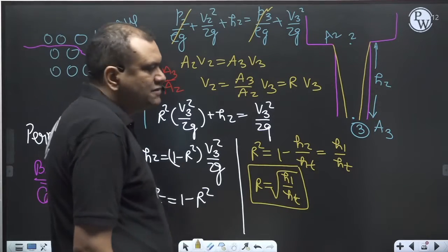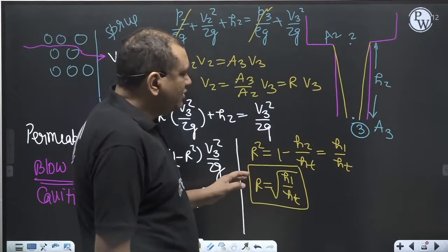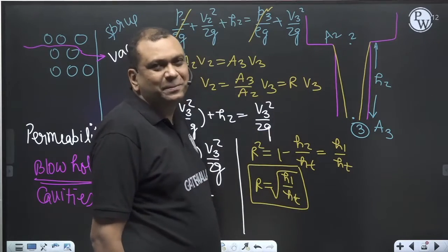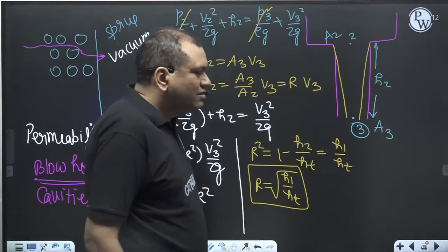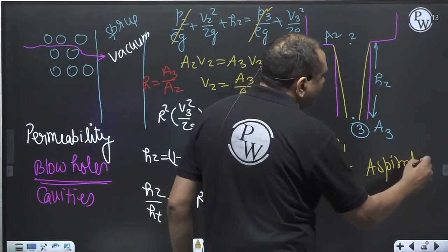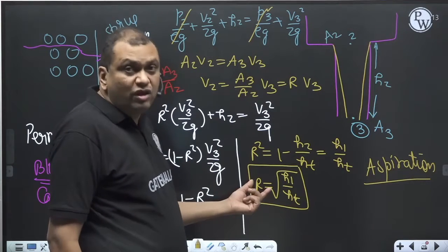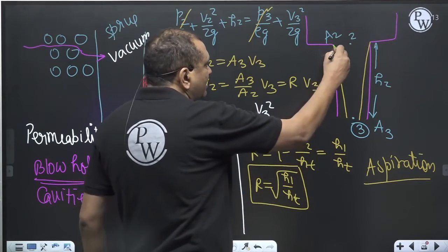So the conclusion is very, very important. In all the gating system calculations, you have to be very careful. When area is decreased in this ratio linearly, pressure will be uniform throughout and the aspiration effect can be avoided. When atmospheric air gets into the liquid metal, this phenomenon is called the aspiration effect. So the sprue should be tapered to avoid the aspiration effect. But see, actually, it will be a little curved.